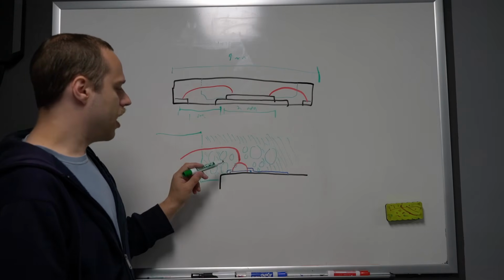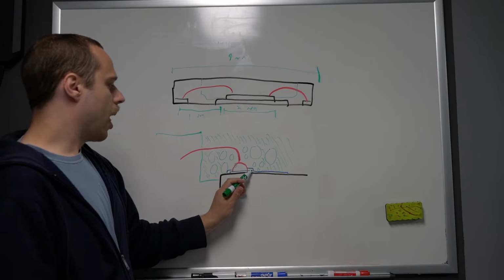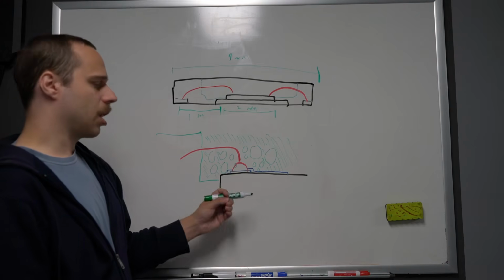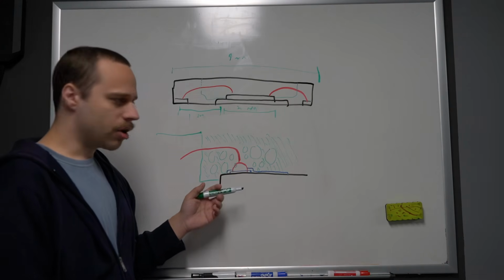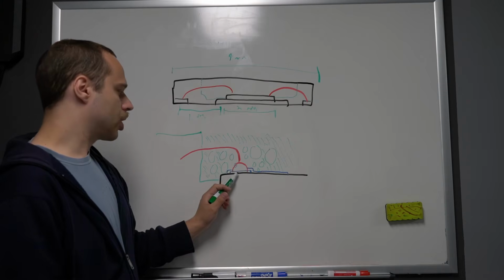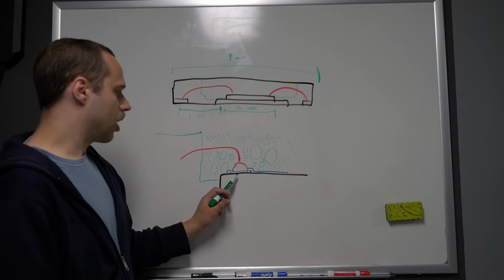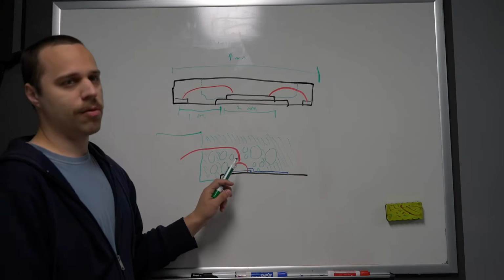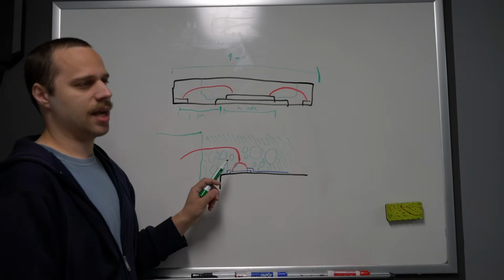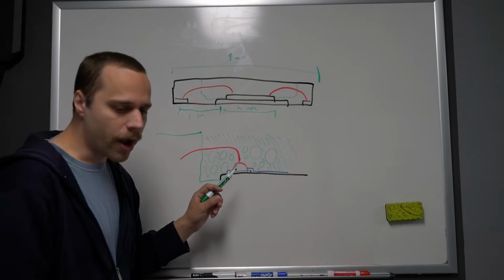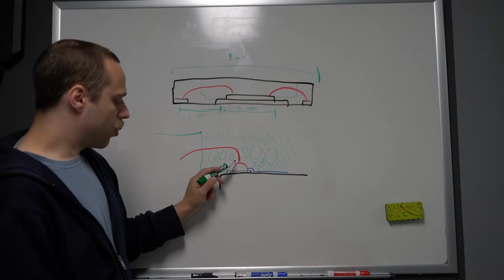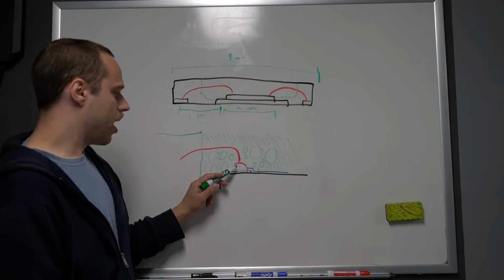Now, the problem is that although the glass passivation layer will protect the die, and the silicon itself is relatively inert to the acid, and the aluminum actually is not too reactive with nitric either, copper is extremely reactive to nitric acid, and it really wants to turn into copper nitrate. So in order to prevent that from happening, we do have to tune the etch mixture a little bit.